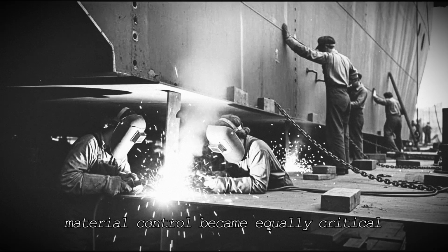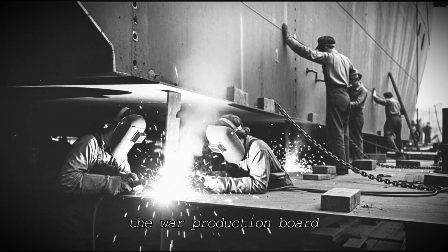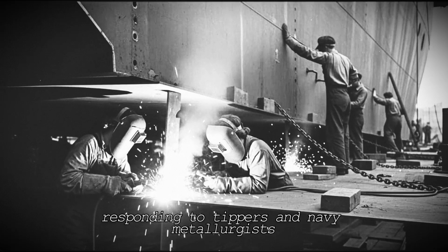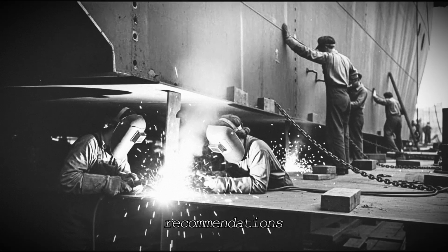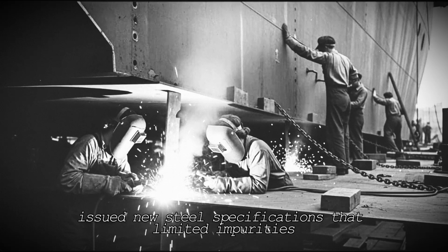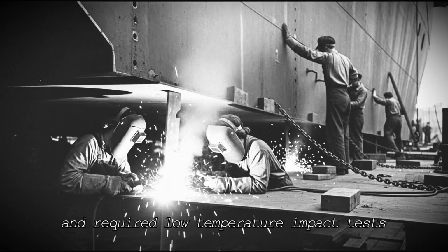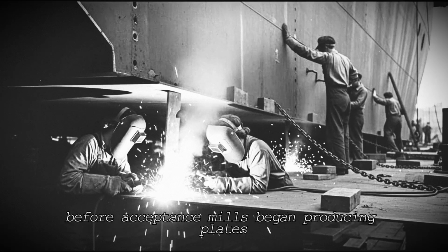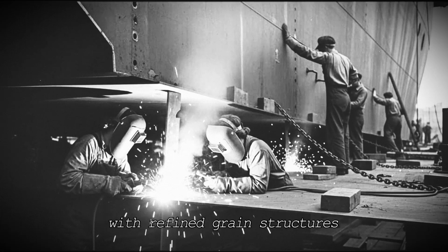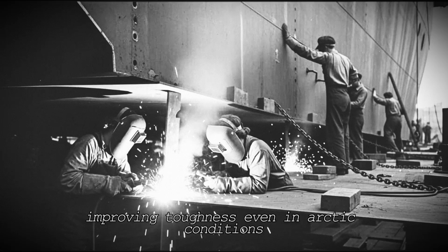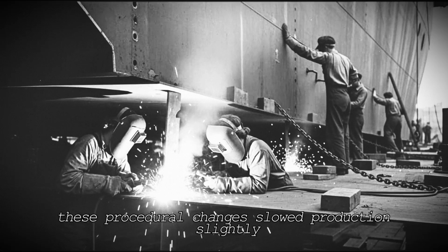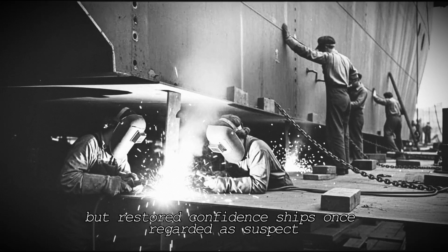Material control became equally critical. The War Production Board, responding to Tipper's and Navy metallurgists' recommendations, issued new steel specifications that limited impurities and required low-temperature impact tests before acceptance. Mills began producing plates with refined grain structures and higher manganese content, improving toughness even in Arctic conditions. These procedural changes slowed production slightly, but restored confidence.